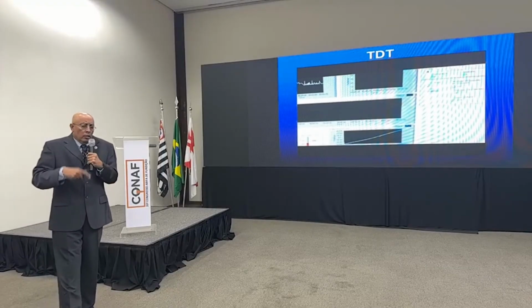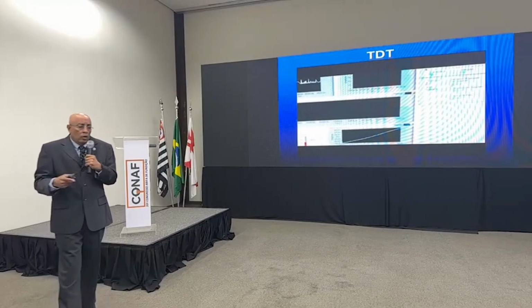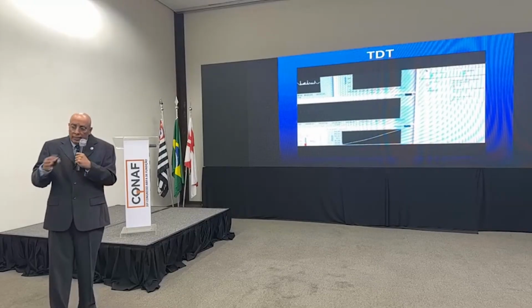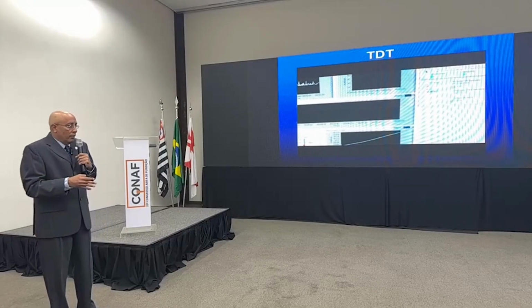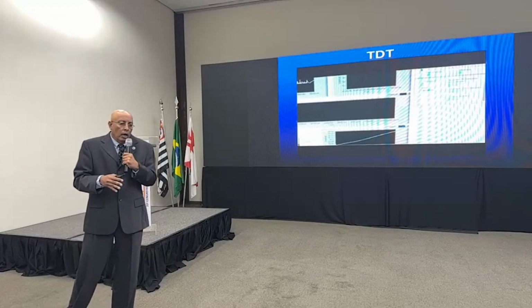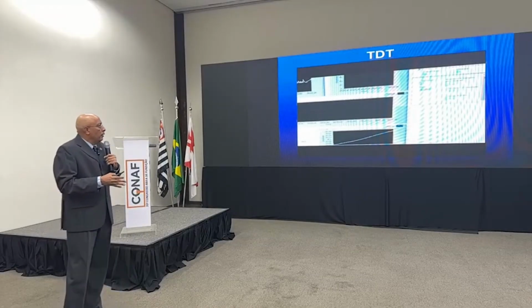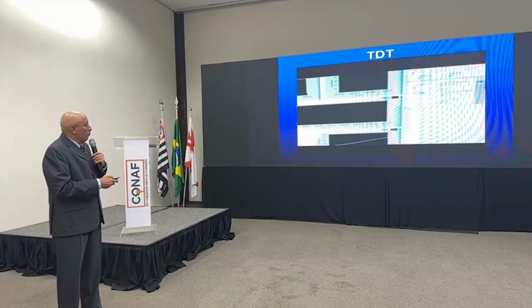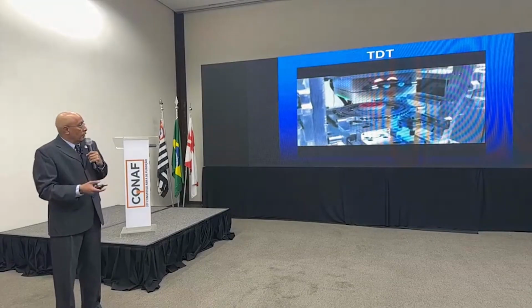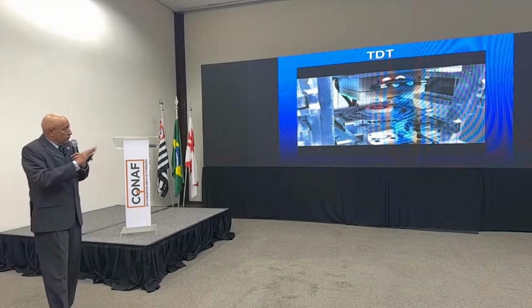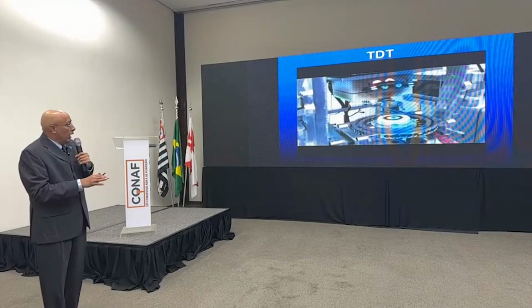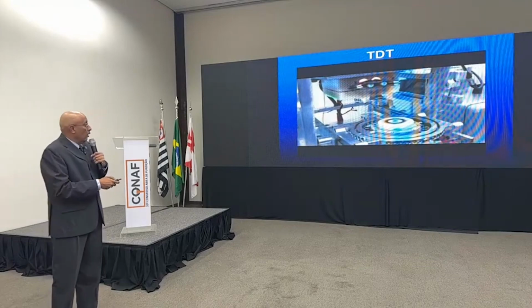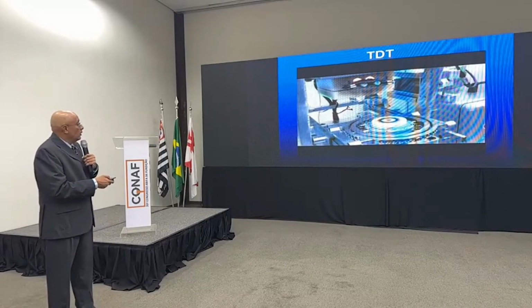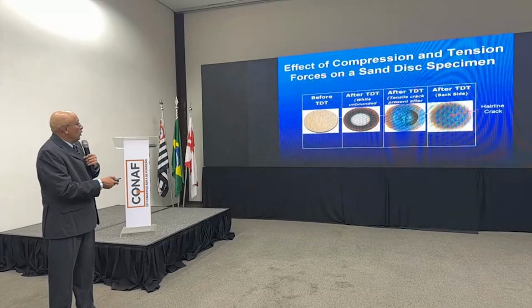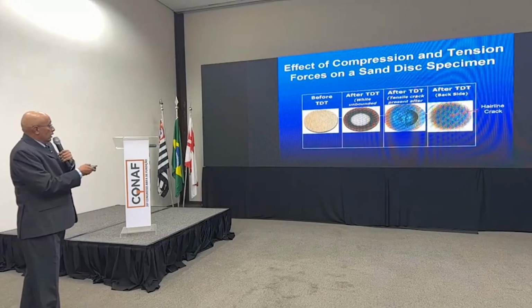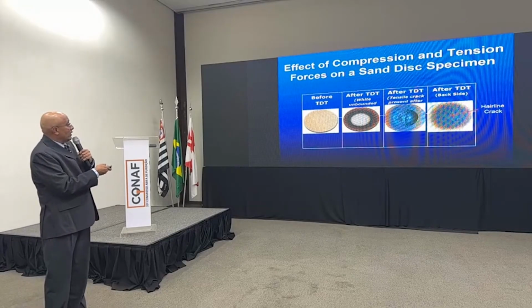The specimen does remain intact so that we could evidence additional data through observations using a macroscope, a 3D macroscope, to get surface roughness data, to get volumetric change data, and to get loss data relative to sand. So this is what the specimen will look like before the test.